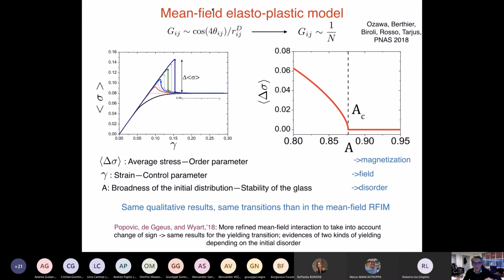We call delta sigma the height of the jump. And you can see in the right curve the delta sigma as a function of A. A is the broadness of the initial distribution. You can see that the delta sigma goes to 0 at a certain value of A. And indeed, the transition goes from being discontinuous in the stress versus strain curve to a critical point. You can see the critical point, the sigma versus gamma curve is the blue line, the dot in the blue line. And then you have an overshoot, and then you have really a smooth behavior for a very small value of A.